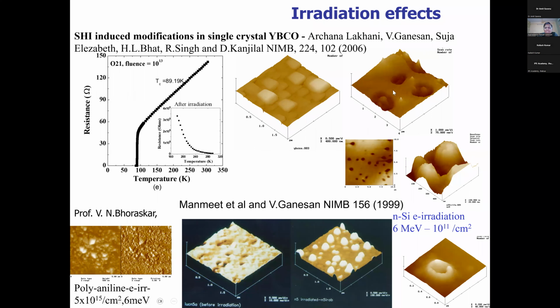When we did it here, you can see that after irradiation, there is a different structure. This is before and this is after. So what happened? Something is eroded away where the grain boundaries are. Then we understood these grains are metallic and grain boundaries are insulating because of defects. Therefore, thermal energy is highly deposited in the boundary. It's called the thermal spike model. These are very interesting structures. Electrons from here cannot go, there is no ohmic connection. So there is non-linear conduction here, as is shown.